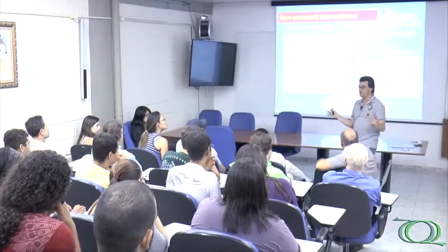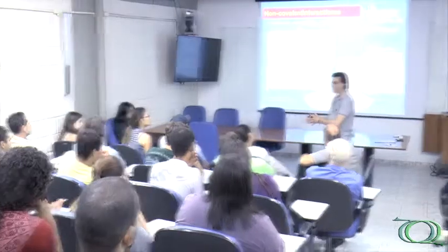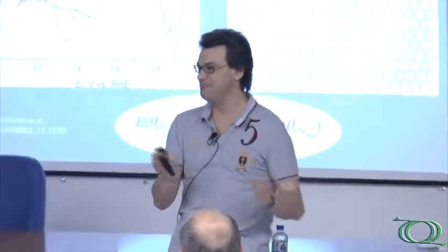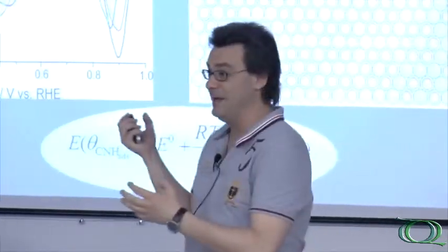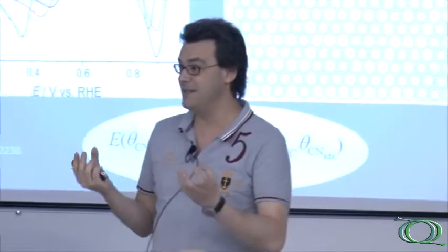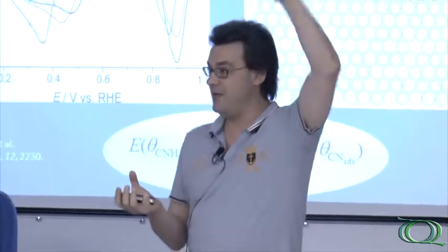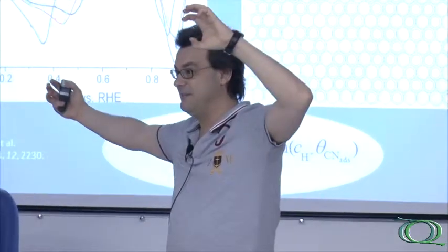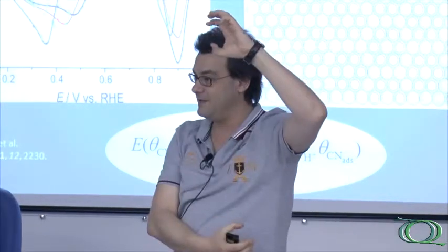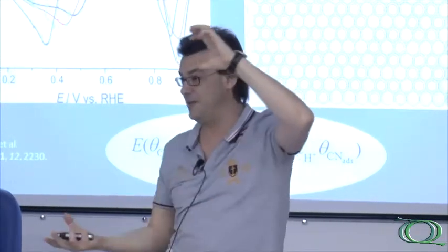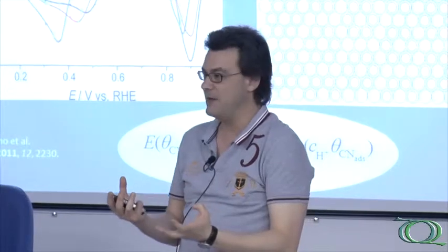But for some reason, without thinking about that, I told him, yes, we will make experiments keeping the cation concentration constant, but first just don't care about that, and then we go further, just to have a bigger set of data. And it was good to do that, because we could see that in some cases with higher concentration, you still have a more positive potential for hydrogen adsorption than at a lower concentration but a higher pH, which is really remarkable.